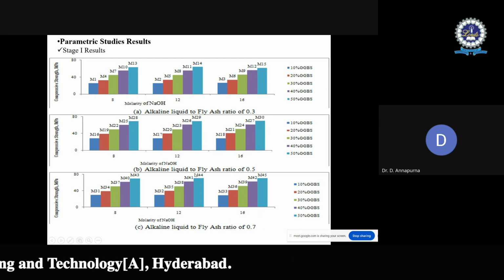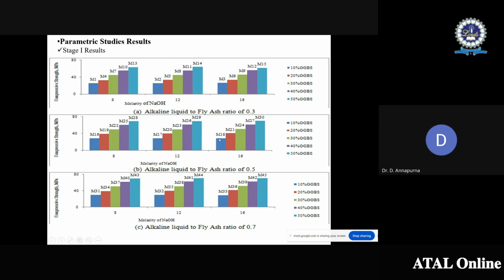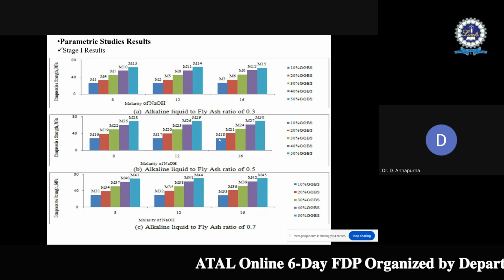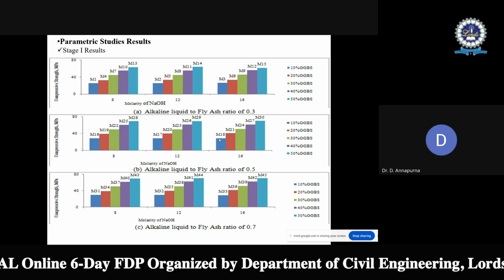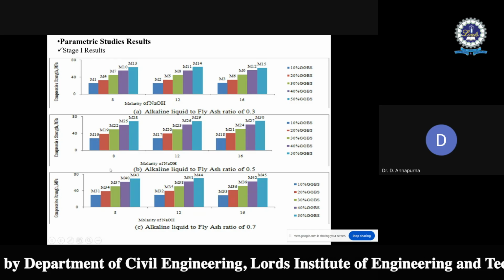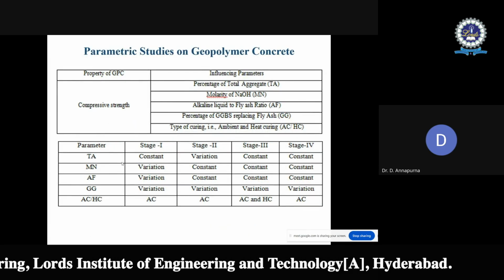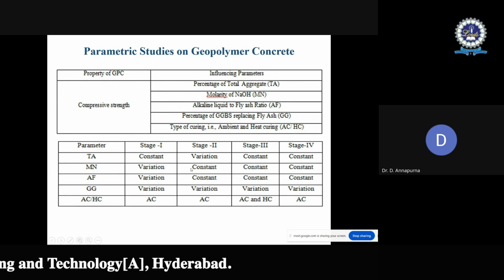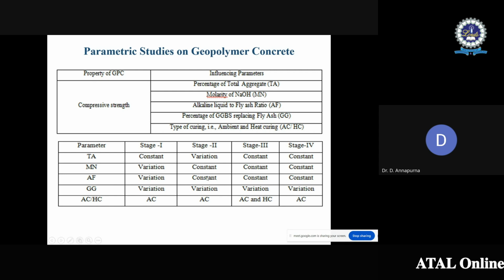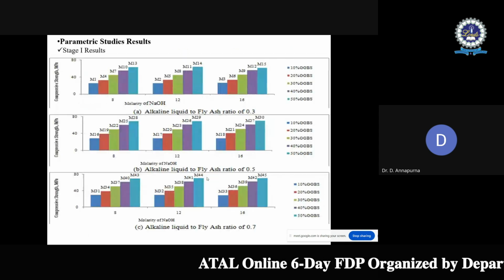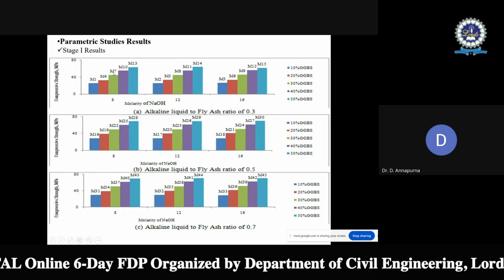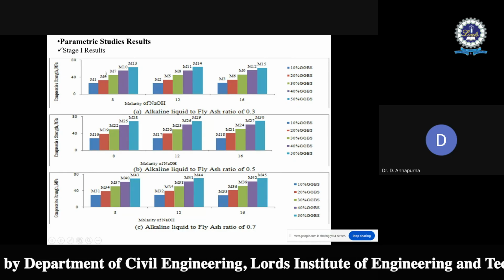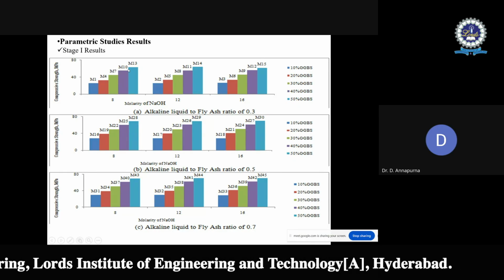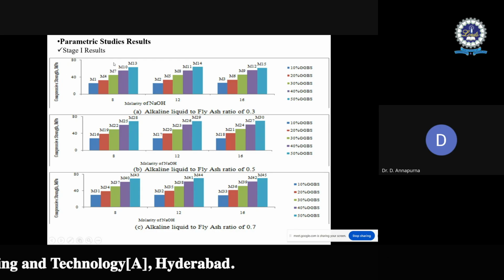Now comes the alkaline liquid to fly ash ratio of 0.5, which gives moderate workability, and it is not consuming much superplasticizer either. So from these stage 1 results, the molarity of NaOH is maintained as 8 and the alkaline liquid to fly ash ratio is maintained as 0.5. At the same time, if you check each set, as the GGBS dosage increases, let us say from 10 to 50%, a compressive strength increment of almost 150% is observed.